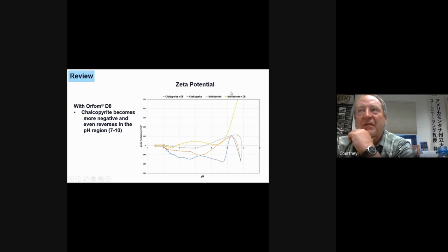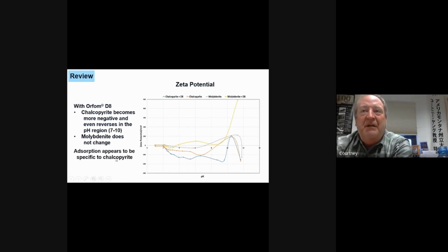So it's telling you that the moly really does not react with the Orfom D8, or the Orfom D8 does not really react with the moly. So the moly really doesn't change. The chalcopyrite really changes, particularly in this pH range from 7 till about 10. And that's where we're most interested. Adsorption appears to be specific to chalcopyrite as a result.